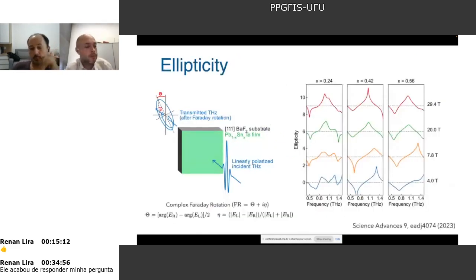Okay, so here I can also take ER and EL and make this combination and calculate the complex Faraday rotation. The real part is the Faraday angle, the imaginary part is the ellipticity. Let's focus only here on the ellipticity. Ellipticity is much simpler to understand. It means if we have circularly polarized light, let's say, for example, only EL, then ER is 0, and ellipticity is 1. And the opposite, if we only have right-handed circular polarization, then ellipticity is -1.